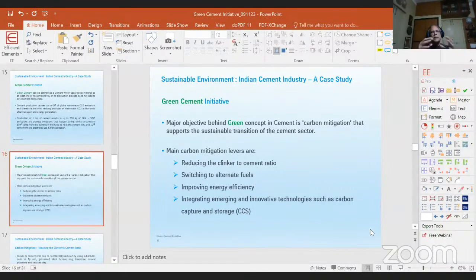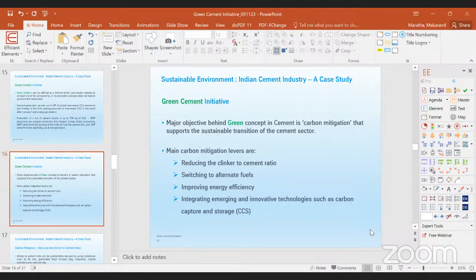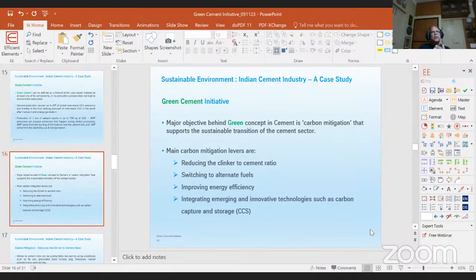Carbon mitigation levers: first, reducing the clinker to cement ratio. As I mentioned some time back, per ton of cement includes 95% clinker and 5% gypsum. This is the classical ordinary Portland cement. But if you have the PPC, the Pozzolana Portland cement, in which fly ash is added to the tune of 30 to 35%, you are indirectly reducing the clinker component, and so indirectly reducing the carbon footprint, because per ton of cement you are reducing the clinker component more and more. So that is how the carbon mitigation levers are defined.